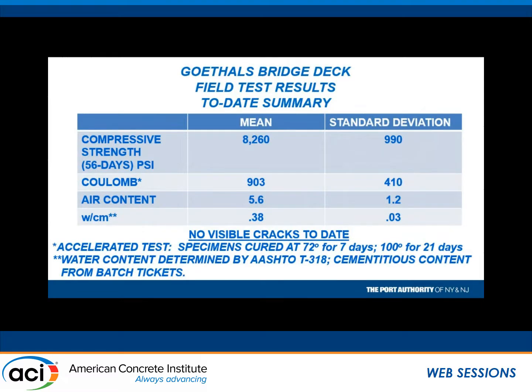Here are the results. Compressive strength, 56 days, 8260. As I said, I don't think we needed the 625 pounds of cementitious material. If you just extract how many PSI we got per pound of cement, we could have taken out 75 pounds of cementitious material, and we would have been at 7,200 PSI. So we certainly don't need all that paste in there. Again, more paste, more potential for cracking.